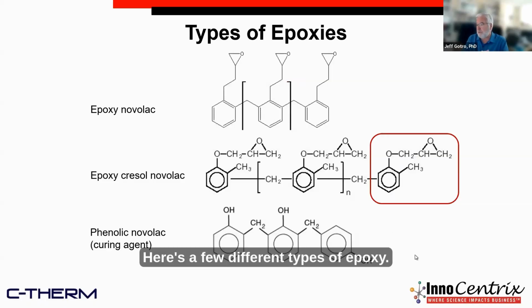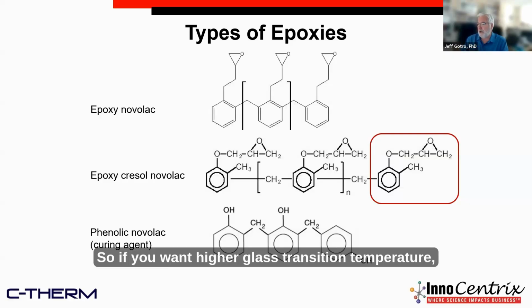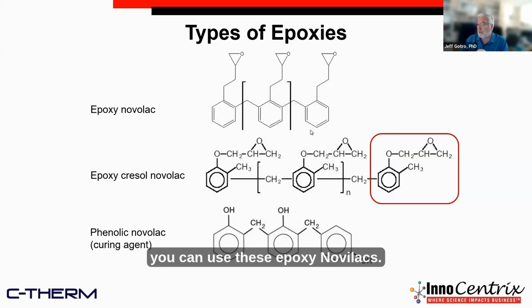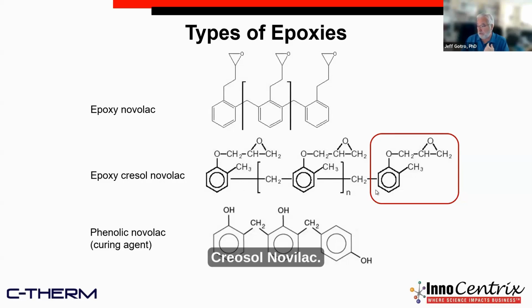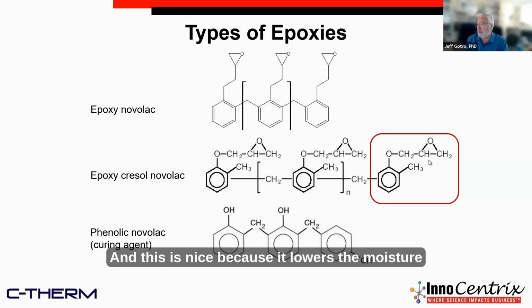Here's a few different types of epoxies. So if you want higher glass transition temperature, you can use these epoxy Novolacs. The one that's primarily used is this Cresol Novolac. It's got this methyl group here, and it's right close to the epoxy group. And this is nice because it lowers the moisture absorption because steric hindrance around this OH group prevents the water molecule from getting into the OH group.